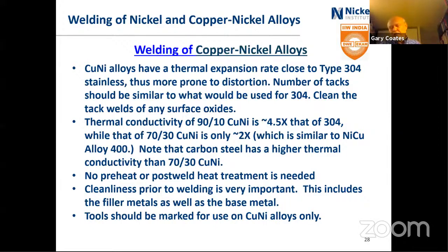So often if you have TIG wire sitting out in the shop, a lot of shops will say that you should take some solvent and wipe down the TIG rod before you start welding on the individual piece. And tools that you work with should be marked for use on copper nickel alloys only. So if you have a tool that's been used on stainless steel previously, you can use it on copper nickel alloys, but then once it's used on copper nickel alloys, you don't want to use it on stainless steel. Copper is a bad actor on a lot of the stainless steels. So the best way of doing it is to have the tools marked for use with copper nickel alloys only.